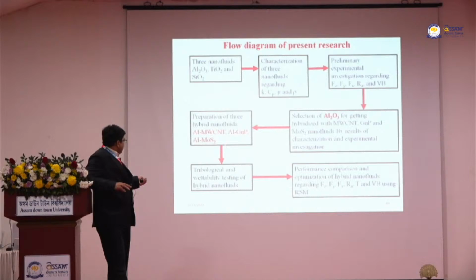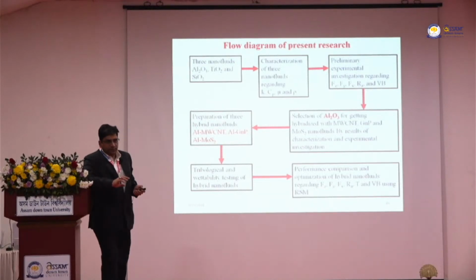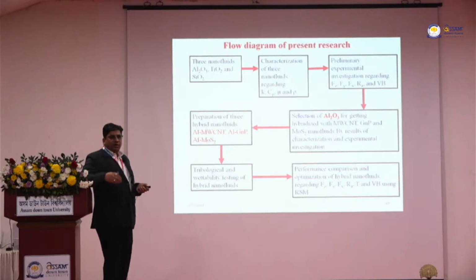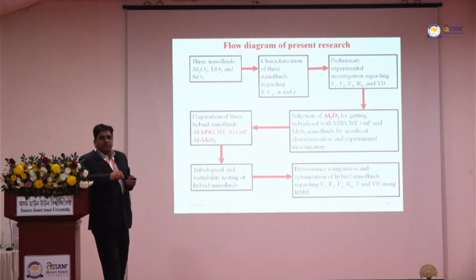So mixing of this. Then we did various investigations, tribological testing, wettability testing, and I will show you the experimental setups so that you can have an idea how it was performed. Then after doing all this, we came to a conclusion that alumina MWCNT yielded the best result. So that was the overall. We tried to sum up the investigation by getting the value with what percentage this hybridization of nanoparticles improved the machining performance. So I am skipping some slides.